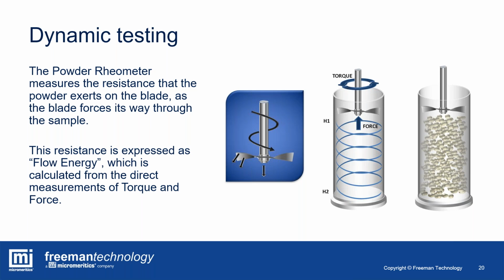And that resistance is expressed as a flow energy, which is calculated directly from the measurements of the torque, so the rotational resistance, the difficulty with which the system resists the rotation, and also the axial force. So it's simple Newtonian mechanics of work done: impose a particular flow pattern and measure the powder's response to it, the resistance imposed. And we call that dynamic testing.